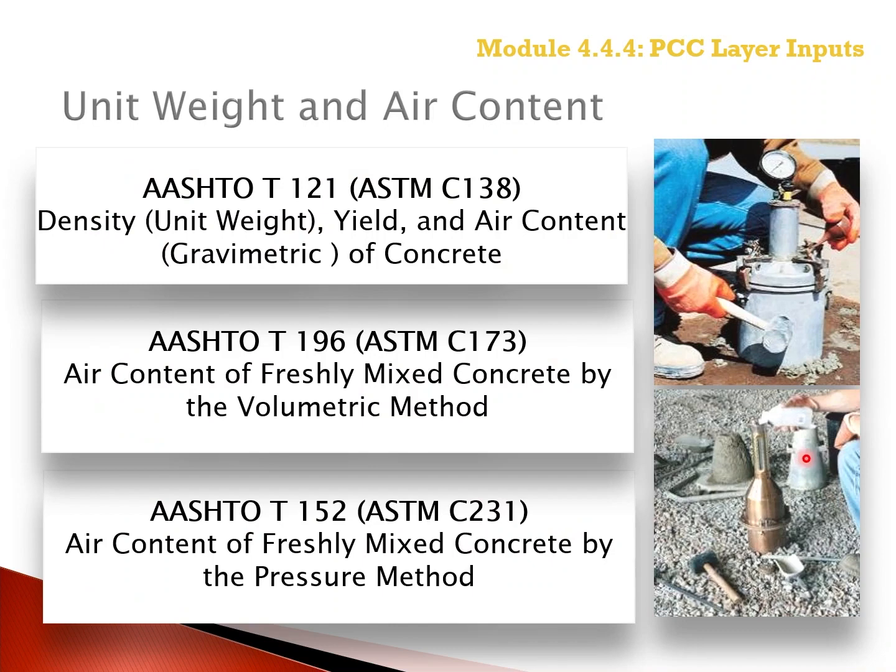Unit weight is important to assess the consistency of the PCC mixture and is an input to the PMAD software. The fresh concrete is measured in a container of known volume to determine the density and/or unit weight in accordance with AASHTO T121 or ASTM C138.